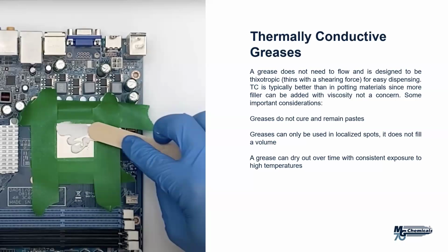Now, the downside is it can dry out over time depending on how it is exposed to higher temperatures, because again, this is a dispersion of oil and filler. And what happens is with high temperatures, you could be evaporating that oil out over time. Then the grease tends to dry out and chalk. And then there's nothing really holding that filler together in any kind of array, so you actually lose performance. That has come up with some major equipment suppliers having used, we'll call it, a cheap thermally conductive grease that dried out and essentially caused overheating in some expensive hardware. So it's very important that you do the work necessary to ensure that you have the right material and that your grease is not going to fail you.